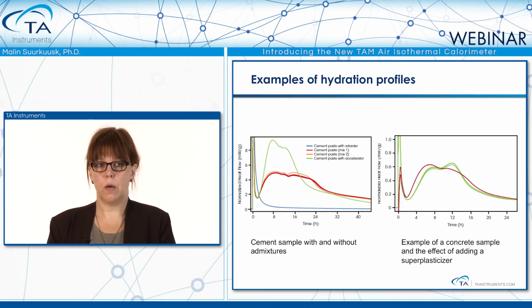The second example is a concrete sample where a superplasticizer is added to the concrete before measuring. Both are duplicate samples. The green curve is without the superplasticizer, and the red one is with the superplasticizer. And we can see that the profile changes with the addition of the admixture.